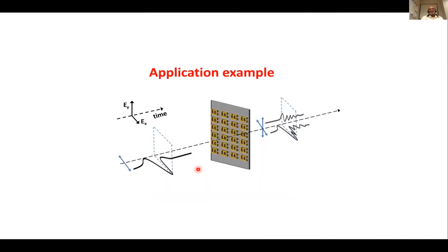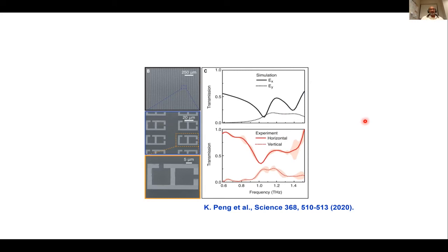And then what she does is that she takes this, makes these terahertz metamaterials. You shine the terahertz pulse through this one. The terahertz pulse passes through this terahertz metamaterial. It interacts with this material, and the polarization of the terahertz pulse changes. She measures the X and Y polarization using our terahertz detector. So here is the electron microscope image of these terahertz detectors, with these terahertz metamaterials she has designed. And then our simulations show terahertz transmission should be like this for the X polarization, and the Y polarization terahertz transmission should be like this.